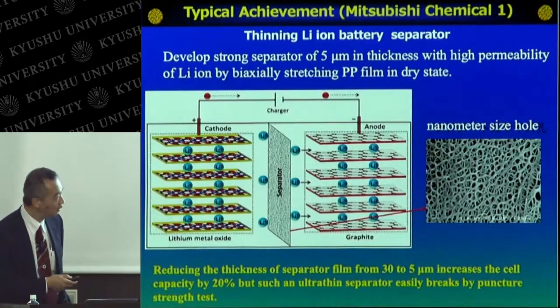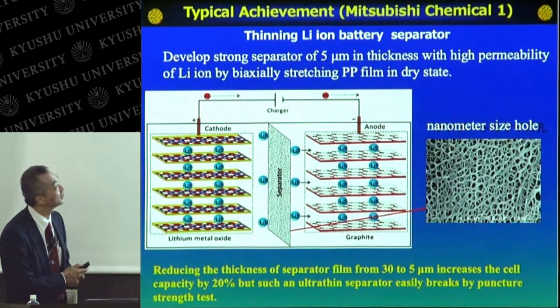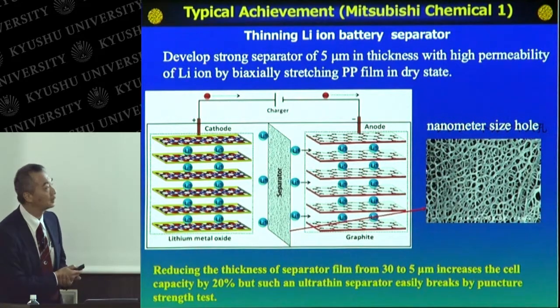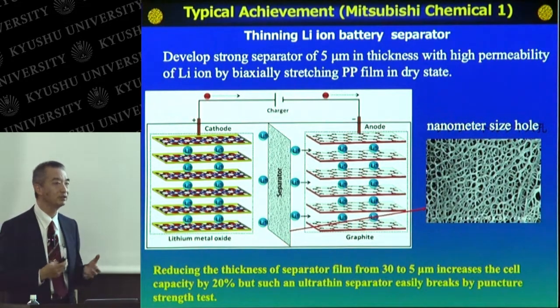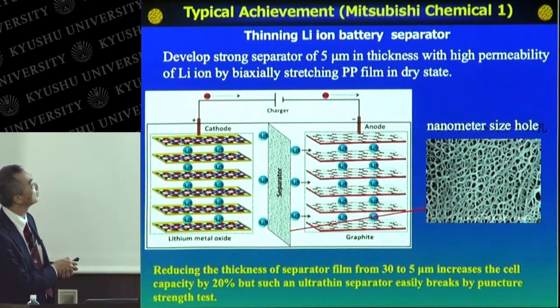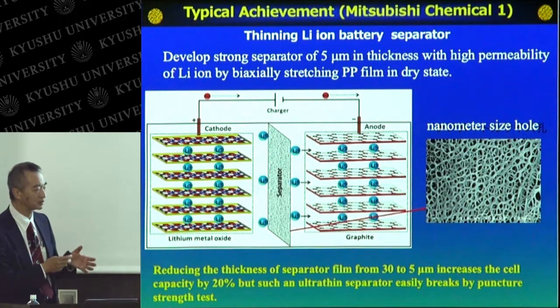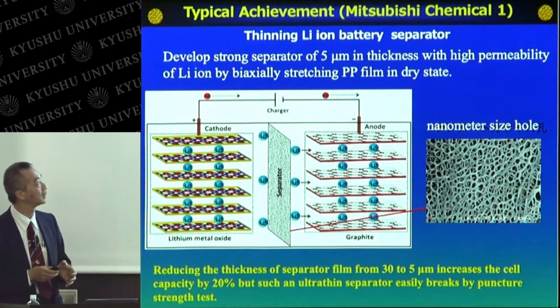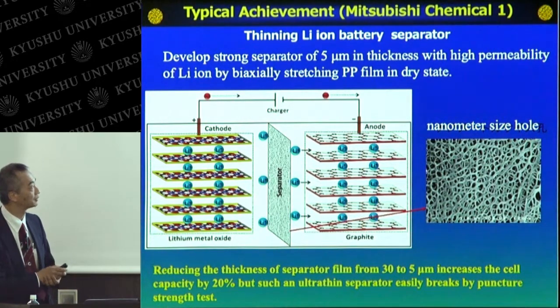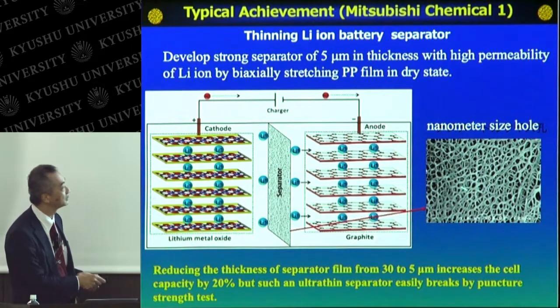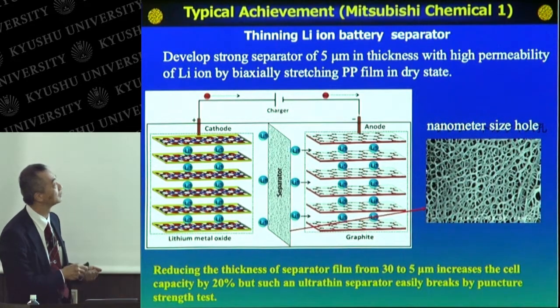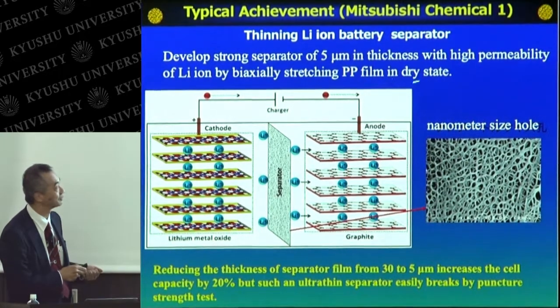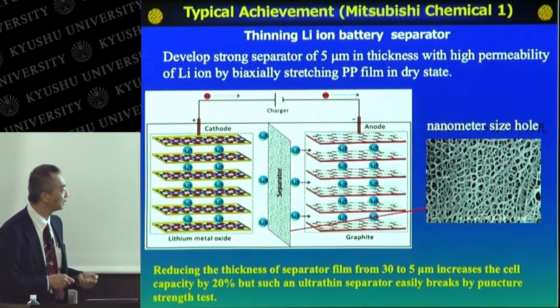Okay. Finally, I'd like to show you the results from Mitsubishi Chemical. They also reduced the thickness of the lithium-ion battery separator. The target is to reduce the thickness from 30 micrometers to 5 micrometers, about 1/5 or 1/6 or something like that. This lithium-ion battery membrane consists of nanometer-size holes in polypropylene films in the dry state.